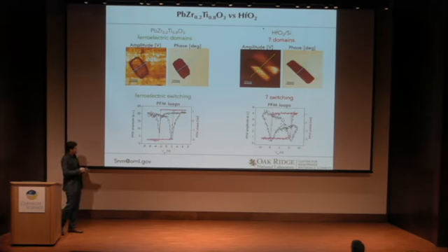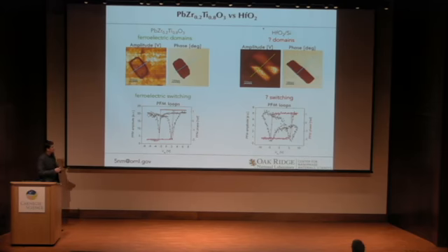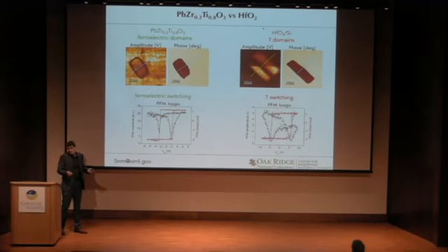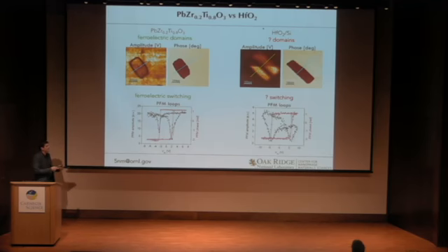If you look at the hysteresis loops, the evidence is even more amazing. Both have a square phase hysteresis loop. The amplitude hysteresis loop here is a little bit less defined than in PZT, but what I would like to draw your attention to is that the presumed coercivity in hafnium dioxide is as large as 5 volts, so it's not a thin hysteresis of some sort. Without some extra explanation, there's no reason to reject that as non-ferroelectric.